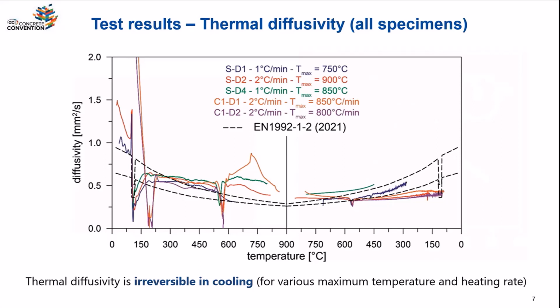So we measure the thermal diffusivity continuously during heating. And then here on the right-hand side, you have the results when we return back to ambient temperature. So a couple of things that we can see here. We have those big peaks, okay? Here it's linked to moisture effects, around 100 degrees C, and here it's the effect of quartz. So these are already known.